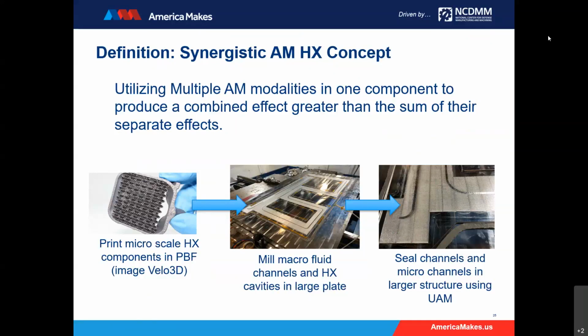So then we can take something like ultrasonic additive, where we can mill in connection channels, fluid passages between each of these discrete locations where we've printed this super optimized organic shape to pull out heat. And then we use the larger process, ultrasonic, to connect all those dots and seal in that powder bed component into the much larger heat exchanger. And this is just a concept. We'd love to try this out, and we probably will someday.